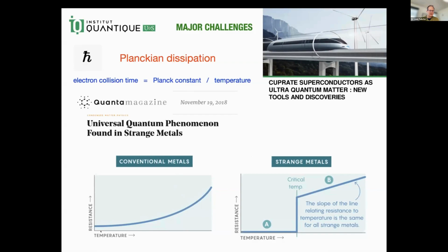In conventional metals, if you measure the electrical resistance as a function of temperature, you find that it varies as the square of temperature. But in certain metals called strange metals, what's found is that the temperature dependence is perfectly linear. Sometimes it undergoes superconductivity, but you can continue to follow this T-linear resistivity to T equals 0. Basically, it appears that this is the manifestation of a new fundamental law of quantum physics, whereby electrons would scatter at the fastest rate they can, dictated basically by Planck's constant. So this is one of the topics that in my group we're very interested in.